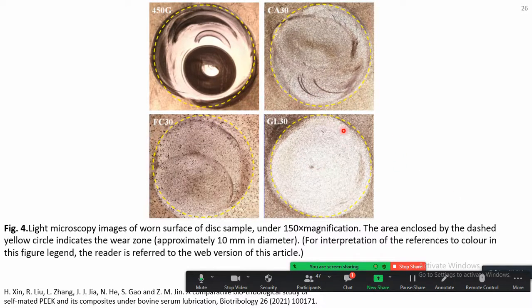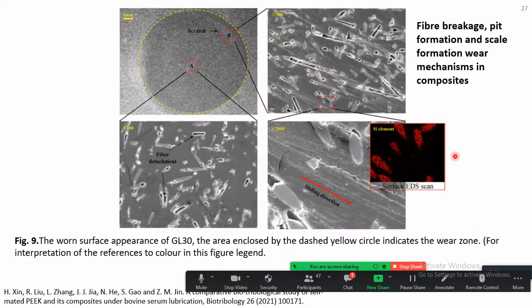The wear surfaces of PEEK show a lot of wear taking place. When we are dealing with composites, the problem of fiber breakage and fiber pull-out leads to pit formation and scale formation. These are the dominant wear mechanisms for composites and materials less ductile than UHMWPE. In those cases, wear particles form because of micro-cracks during the wear process. Wear is also a fatigue process on the surface — cracks initiate, grow, and a wear particle is released, accelerated in non-ductile or composite materials.